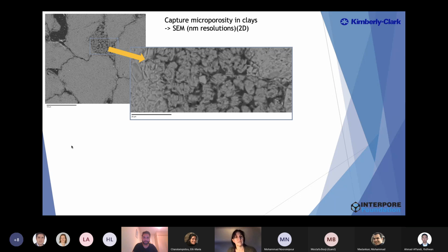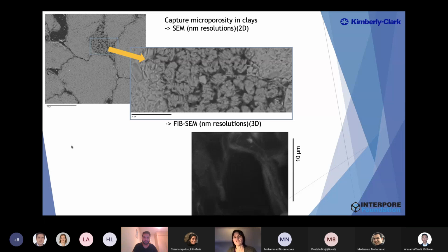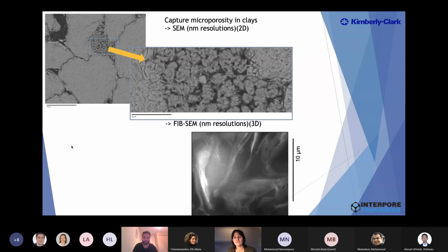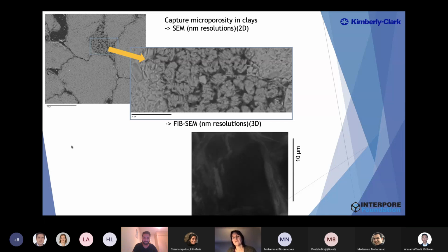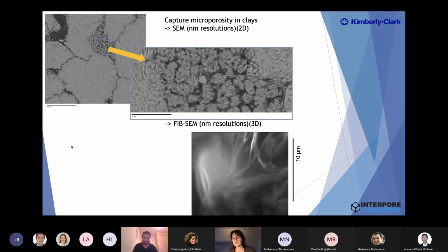So you combine this by examining it with scanning electron microscopy, which is of course then in 2D, allowing you to get nanometer resolution. If you want to go for 3D at nanometer resolution, often people use focused ion beam scanning electron microscopy, because then we can get the structure in 3D.